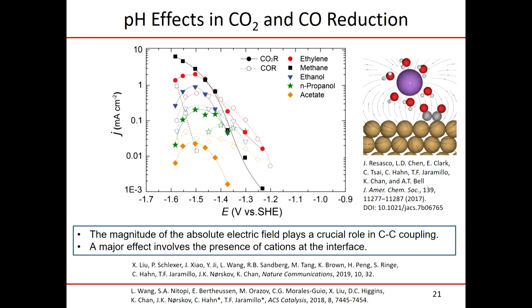And so if you're a cation like a potassium or a lithium or a cesium hanging out at the interface, you don't care what the RHE voltage scale is. You just care about the absolute magnitude of the potential. So say an SHE scale or a silver chloride scale. And it turns out when you plot the same data in that way, you see a lot of overlapping of the C2s, though interestingly, C1 chemistry, methane, is easier to make from CO2 than it is to make from CO. And we think that's because in those conditions, in base and CO reduction, you're depleting the carbon intermediate by making C2 so fast you can't hydrogenate it all the way further to make the hydrocarbon methane.